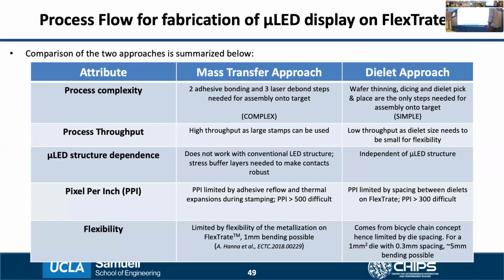Then, however, in the case of the dielet approach, it's completely independent of the micro LED structure that we use. In terms of resolution or the PPI of the display, the mass transfer approach is really limited by the amount of adhesive reflow that we get during the stamping process, as well as the thermal expansions during the bonding. A PPI of up to 500 we discovered was possible, but anything more than that was very difficult due to the reflow of the adhesive.